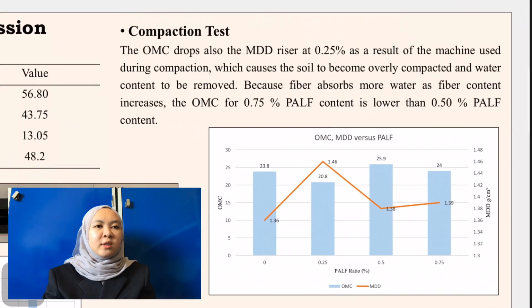Next is the result of the compaction test. The compaction result showed that the maximum dry density increased but decreased at 0.5%, and optimum moisture content decreased but increased at 0.5%. The findings show that the pineapple leaf fiber has been proved as a potential material in enhancing soil efficiency, which is proved by the direct shear test that revealed that the value of cohesion and internal friction increased until the fiber content of 0.75% was reached. The OMC dropped also. The MDD rose at 0.25% as a result of the machine used during compaction, which caused the soil to become overly compacted and water content to be removed.